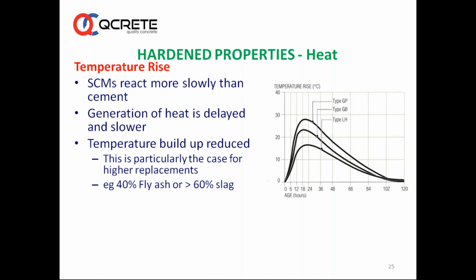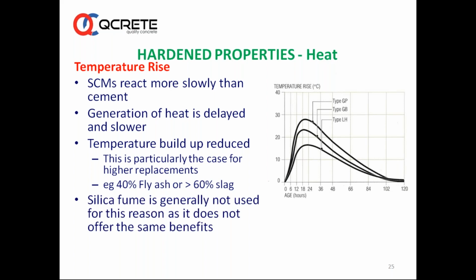We already touched on this, about the heat buildup. SCMs react more slowly. Why do SCMs react more slowly? SCMs will wait for calcium hydroxide to form, and the SiO2 of SCMs or the pozzolanic materials will go and meet calcium hydroxide and start consuming it for forming further calcium silicate hydrate gel. So there is a delay in the progress of heat buildup. For all mass concretes and mass foundations, the preferred material is either 70% GGBS plus 30% OPC, or a minimum of 35 to 40% fly ash. All these higher replacements have been found to significantly contain the heat buildup. Okay, next one.